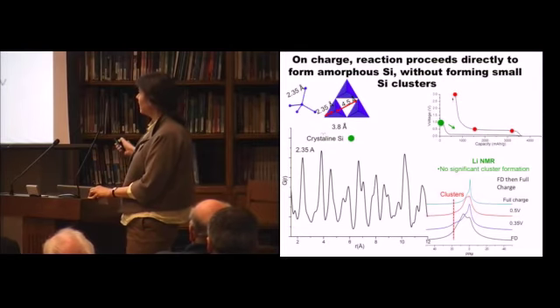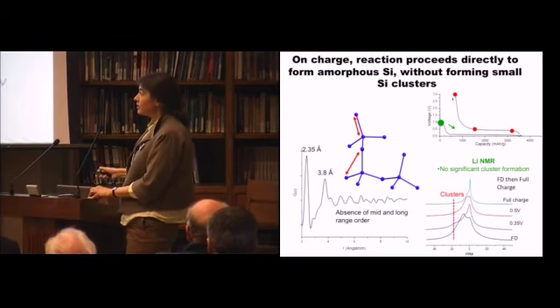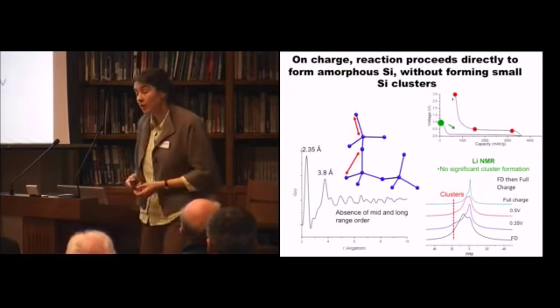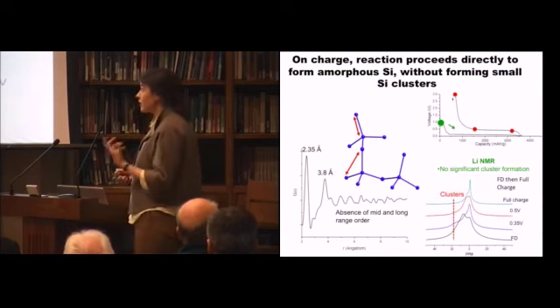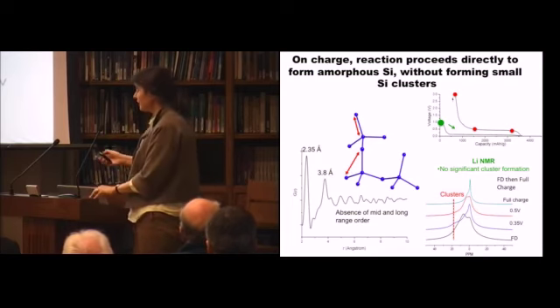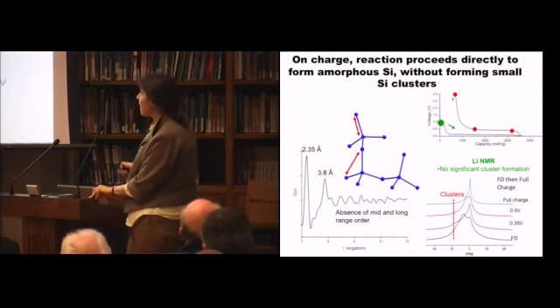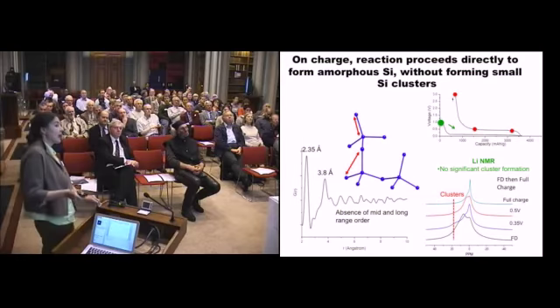You can cycle it to deep discharge and then up again on charge, and you can see it's converted to an amorphous structure with no long-range structure, but you still have two peaks here that come from the tetrahedra in the material. So you can see that the amorphous structure is still built up of these silicon tetrahedra. And then you can look at the NMR on charge of this material, and you can see that it goes back without forming any clusters on charging.